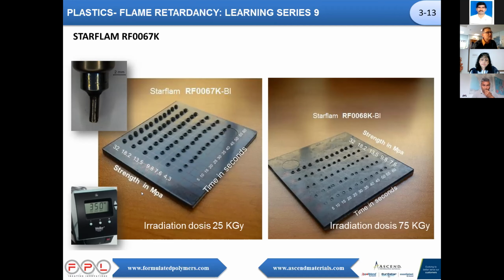And if you see this part irradiated now 75 kilogray, which is much more, you see the print of a pin is much lower, meaning that for example at 7 megapascal, we can say that it can survive almost 1 minute. Of course, if we would need to survive a higher weight for a higher period of time, you will have to increase the doses applied.